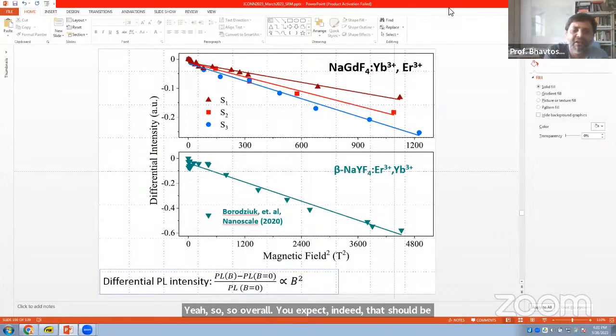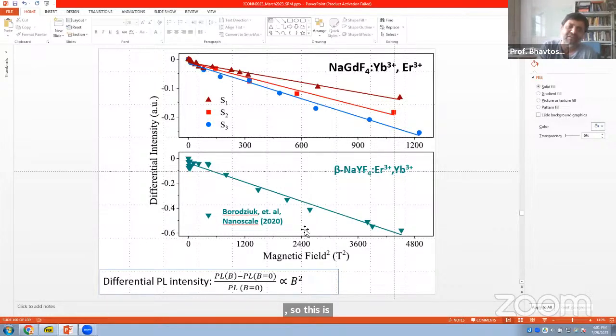This is again some other published result where people have done measurements to much larger fields, and here too one finds that you do see a B² dependence. So this is another application where you can see that systematically the luminescence is changing with magnetic field, and we can try to understand the underlying physical process by looking at the change in luminescence.